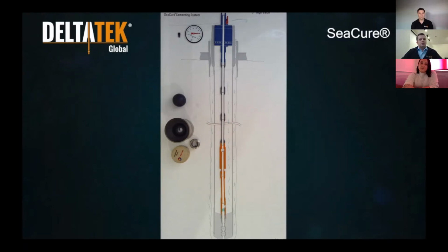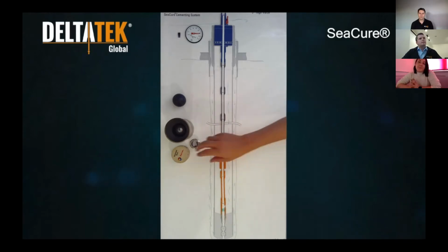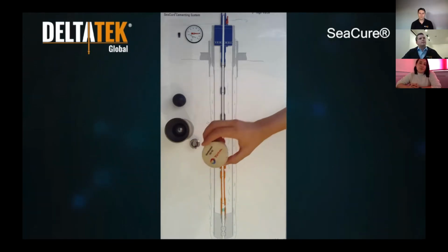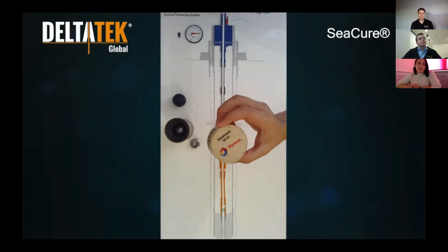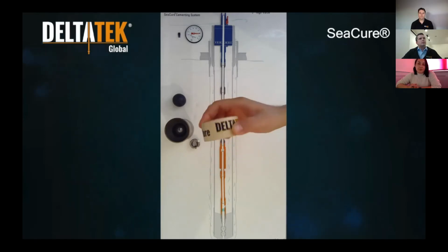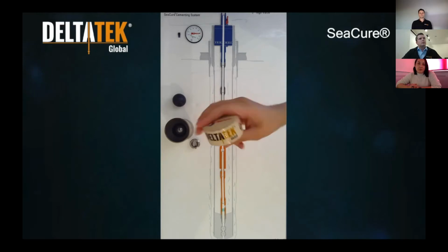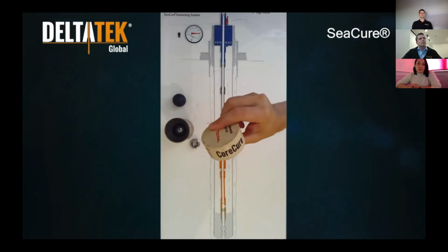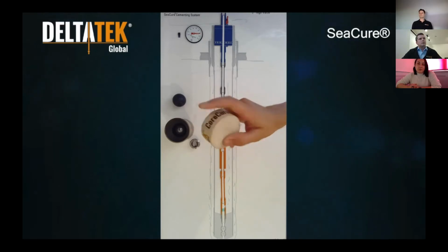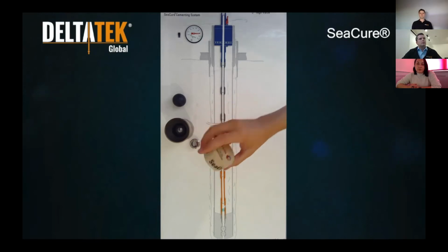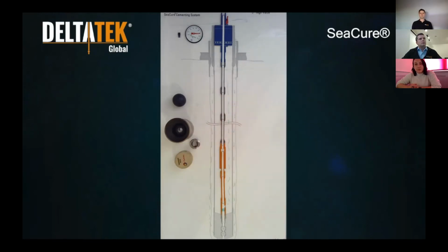However, one unique aspect of the ball drop version of SeaCure is, because of the positioning of the ball seat within the latch-in adapter, 14 inches off the nose, for jobs that wait on cement, it's possible to retrieve a down-hole sample of cement from the shoe itself. We call this feature Core Cure, an albeit qualitative but definitive example of the quality cement you have at the shoe. The remainder of the SeaCure process is identical for any of the versions selected.